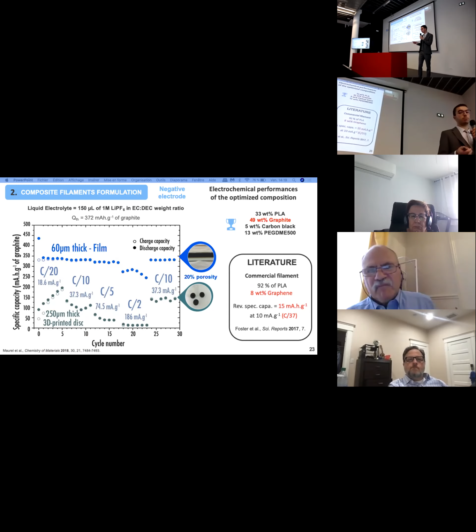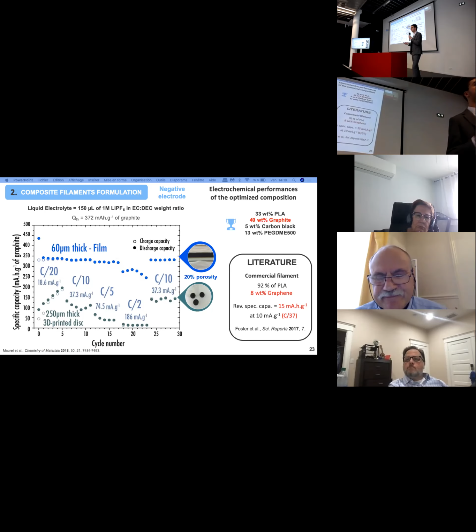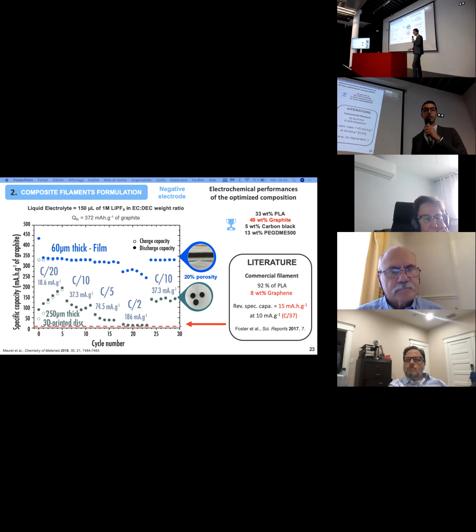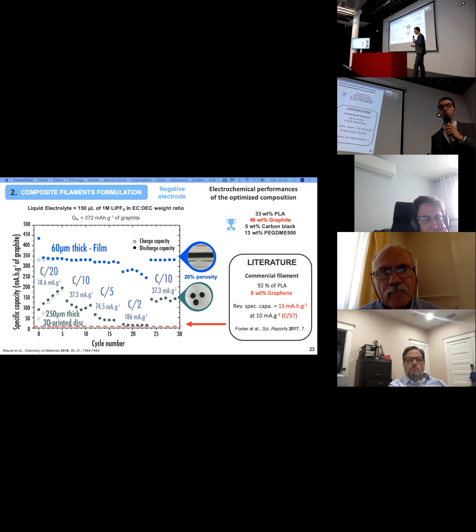So maybe you will think that these electrochemical performances that we got are quite low, and you are right. In comparison with commercial lithium-ion, of course, they are quite low. Nonetheless, I just wanted to share with you this. In comparison with the commercial filaments that I introduced at the beginning of this part, the commercial filaments that contain 8% of graphene, here you can see represented in the graph by the red line the reversible specific capacity that was obtained thanks to this commercial filament. That was only 15 milliampere hours per gram. So even if our performances are quite limited, I agree, they are still much better due to the huge amounts of active material that we implemented within our homemade filaments.